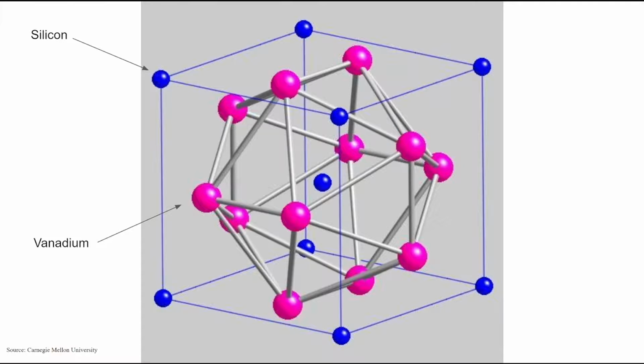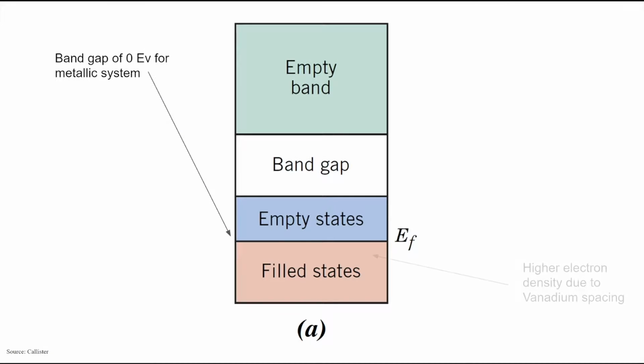At low temperatures, the cubic lattice may soften, extending several percent into a tetragonal lattice as a result of the strained vanadium-vanadium single bond. This is a martensitic transition with very little change in the unit cell volume and total energy, therefore not affecting the crystal's critical temperature significantly.